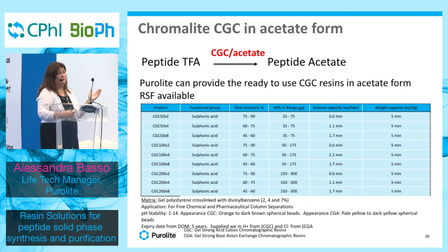A nice application in the peptide synthesis is when you cleave the peptide from a solid phase, you get the peptide in a trifluoroacetic form, and you need to transform the peptide into the acetate form, ready to be lyophilized. So we can provide the resin in the acetate form for ion exchange, that you can use directly to do the transformation. And since it's the final step in your peptide synthesis, we also provide all the regulatory support files. So it's a resin that you can use in pharmaceutical production.